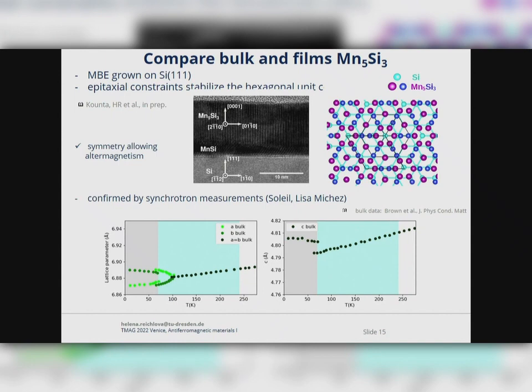The important thing is that when it's grown on this silicon 111, it stabilizes the hexagonal unit cell in the full temperature range. This is a very important thing, and I will come back to it later. And it's so important that we put additional effort to really confirm this assumption or this suspicion which we had.